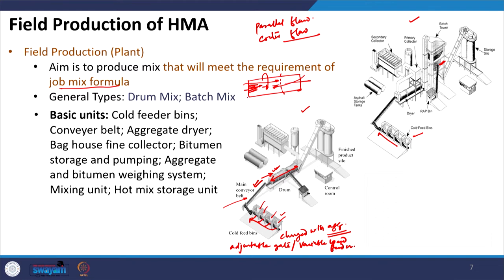In the parallel flow system, aggregates are fed from the burner side and move through the drum to the discharge end. At approximately one-third distance from the discharge end we have the bitumen feeding system. At this location bitumen is fed and mixed with the aggregate, and then the entire mixture gets discharged. Very near the bitumen we also add filler — the reason for adding filler in close proximity to the binder is to trap the fines, which keep moving due to the heat inside. The filler will be trapped and coated by the bitumen.